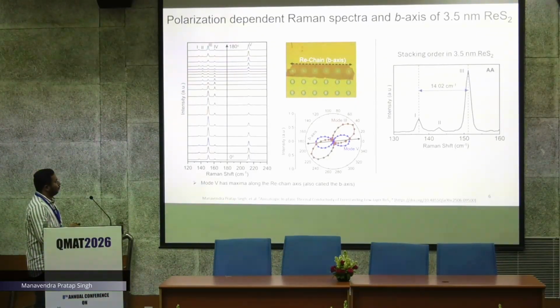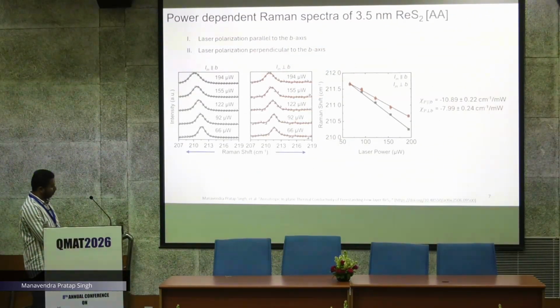One more thing we have to check in this material is the crystallographic axis, because I have to see the anisotropy. So we perform polarization dependent Raman spectroscopy to see where the Re chain, or b axis as people generally call it in this material, is. Mode 5, like this mode, has maxima along the Re chain, which is called the b axis. This we can see in the black double arrow. So this is the Re chain confirmed by the polarization dependent measurement. And I was telling that the stacking order we can calculate from the difference between the third and first mode. Here we can see it is 14.02, so it's AA stacking. So we will perform the temperature dependent and power dependent measurements on this AA stacked sample.